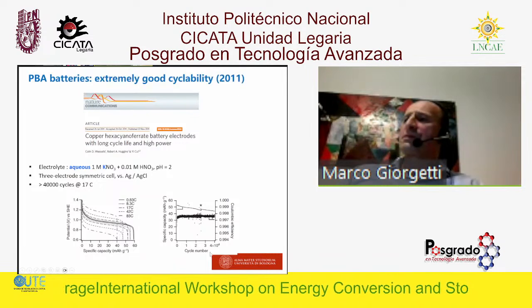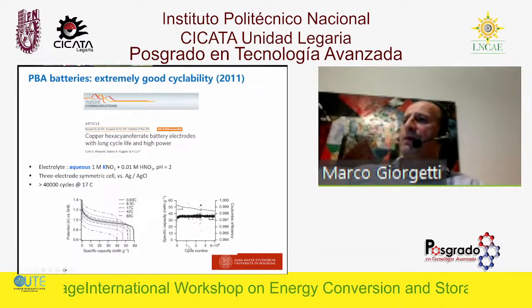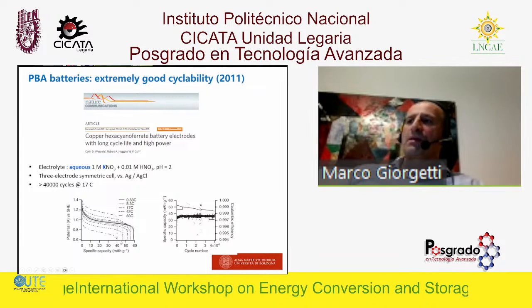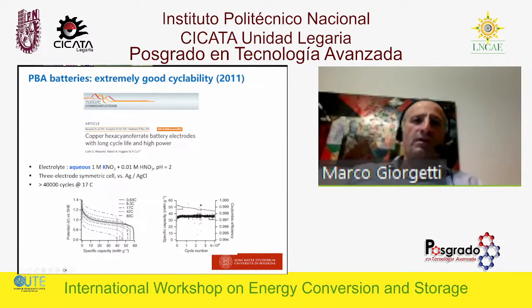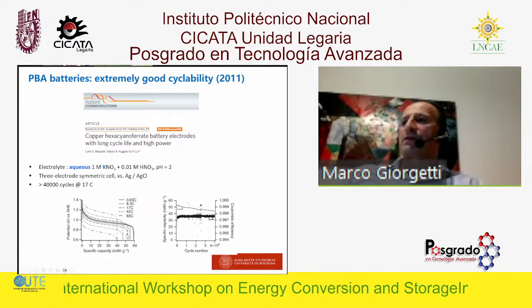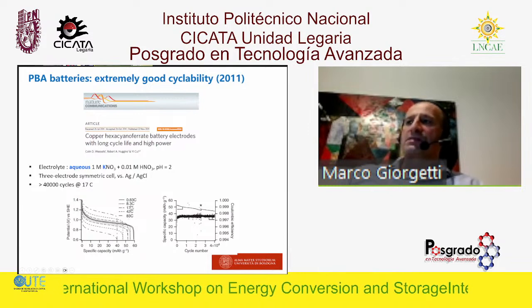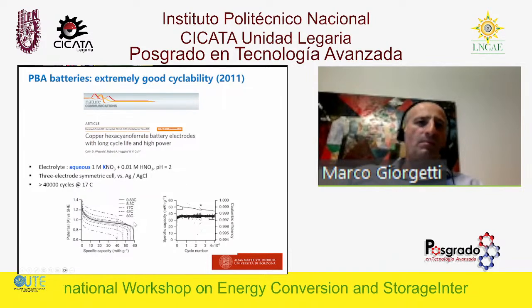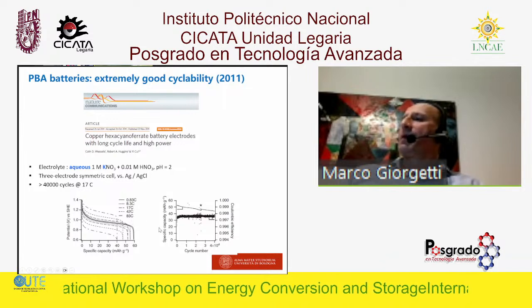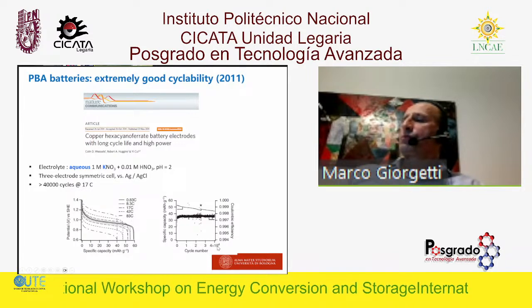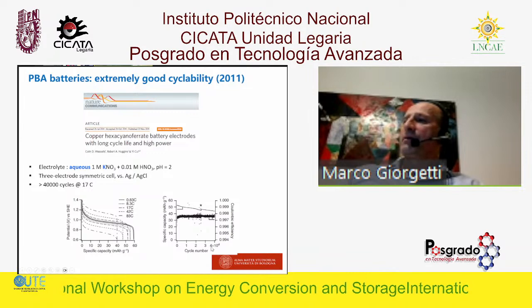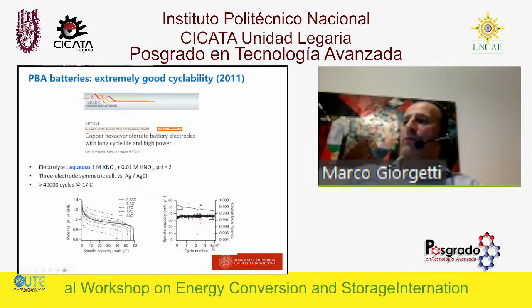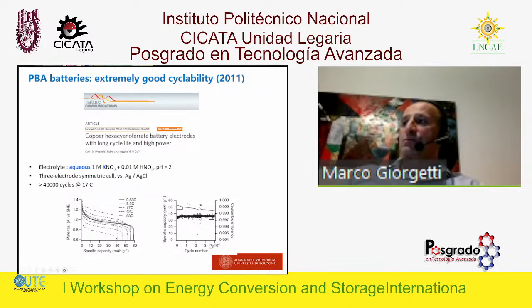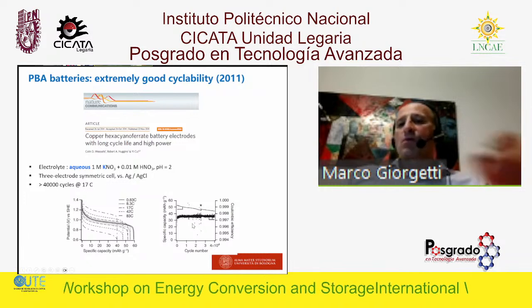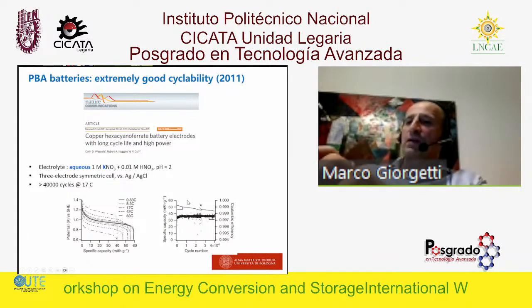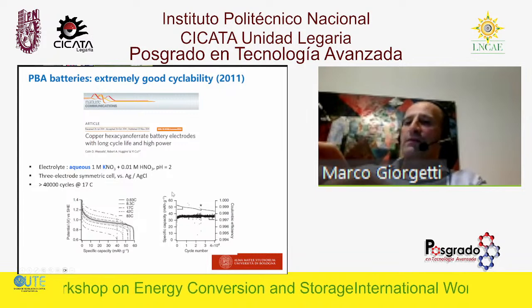Anyway, what was the good point? The good point can be seen from here, the cyclability. Because even though the specific capacity is not large, it's very low, 40, 50, 60, depending on the C rate, the C rate is extremely interesting. This material was capable of performing quite a high number of cycles, 40,000 cycles. So this has motivated a lot of people to start to look at that.